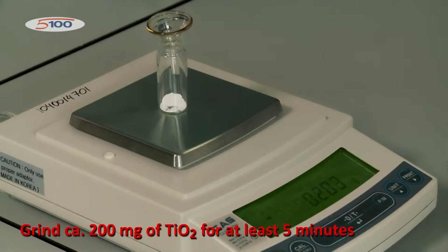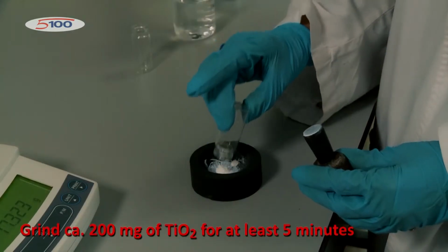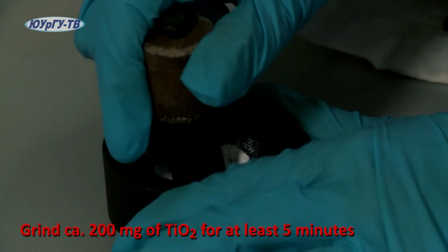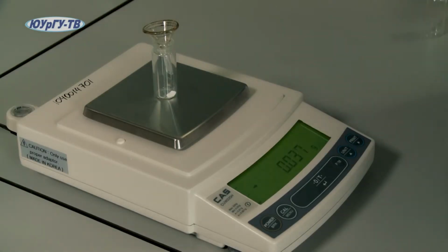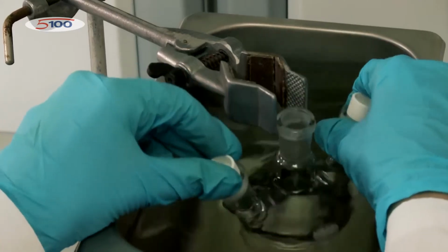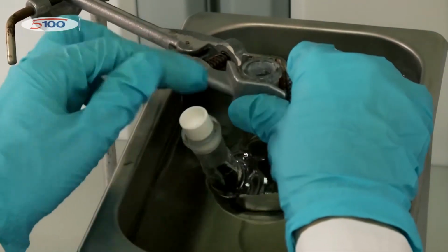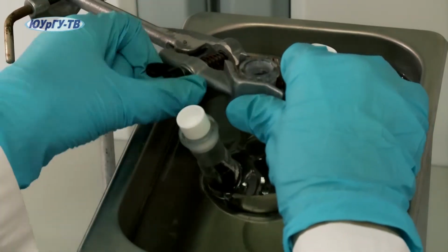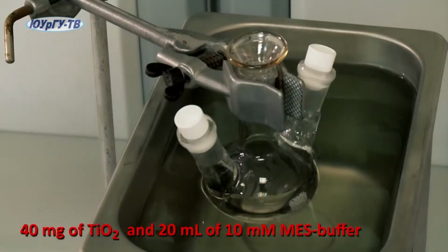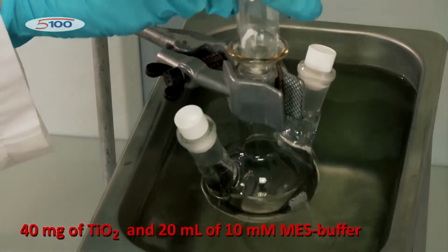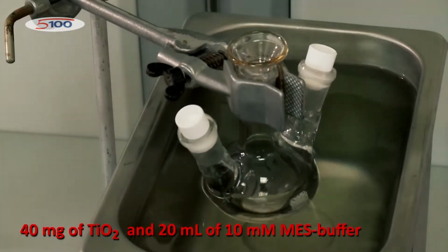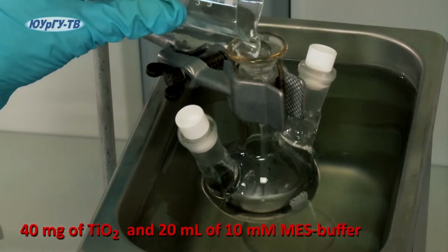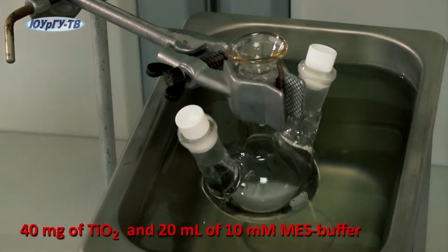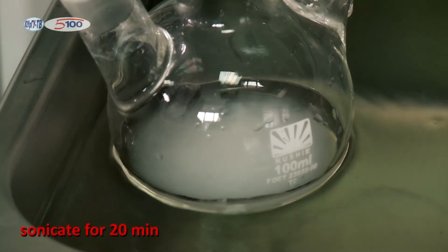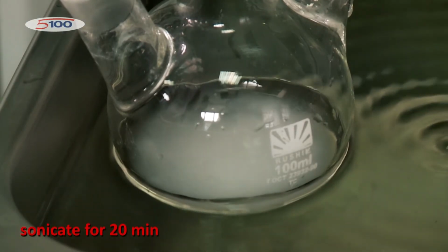Grind approximately 200 mg of nanocrystalline titanium oxide in a mortar for at least 5 minutes. Weigh 40 mg of ground titanium dioxide nanoparticles into the laboratory flask. Put the flask into the sonication bath using the laboratory stand. Add 20 ml of 10 millimolar MES buffer solution into the flask with titanium oxide and sonicate in an ultrasonic bath for 20 minutes.